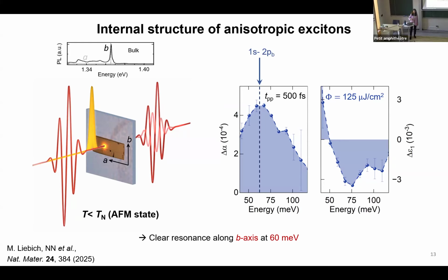Why do I call it a 2p_b transition? Because when we flip the mid-infrared polarization to the A direction, first off, we see a very damped response because of the lack of the dipole moment in this direction.